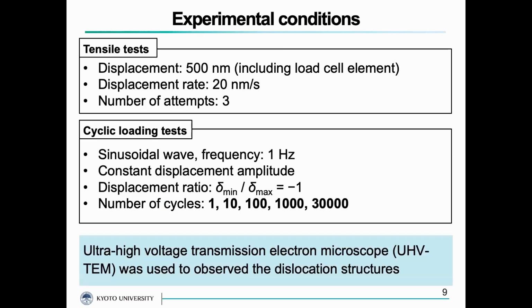To eliminate equipment dependence, we conducted tensile and cyclic loading tests using the same experimental system. First, we conducted 3 tensile tests, and then conducted cyclic loading tests under constant displacement amplitude to satisfy a resolved shear stress amplitude lower than CRSS from the tensile test.